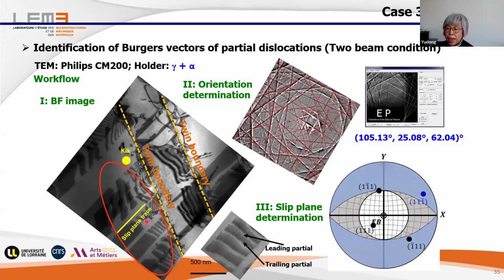And now, if we make a trace analysis, you see the trace is here, and we put it here. And now, you see each pole corresponds to a 111 plane, and this pole is given by its normal direction, normal vector. And so the normal vector is outlined by this dashed line, and the plane trace should be here, perpendicular to this dashed line. And then we see this trace is exactly this 111 plane.